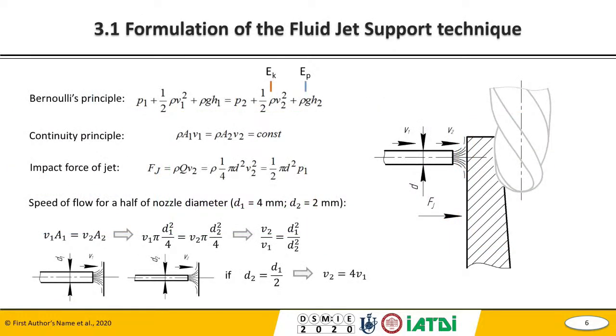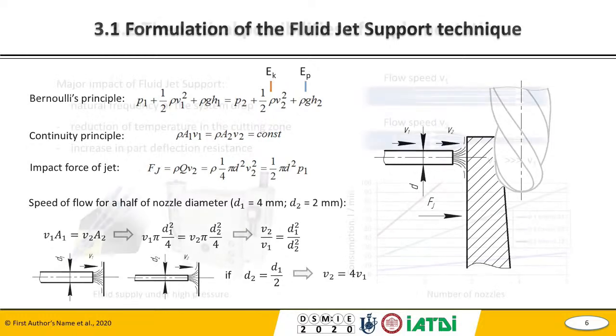So, formulation of the fluid jet support technique. Based on Bernoulli's principle and the continuity principle, we get the impact of the jet force. Also, the speed of the flow is defined, and we find that with a halved nozzle diameter, it's 4 times higher. The pump pressure, of course, is constant, but there are different types of pressure in the flow: static, dynamic, hydrostatic pressure. So by increasing the speed of the flow, we increase the dynamic pressure component and accordingly the kinetic energy of the flow. So there is a high force impact on the thin-walled part. Next slide, please.